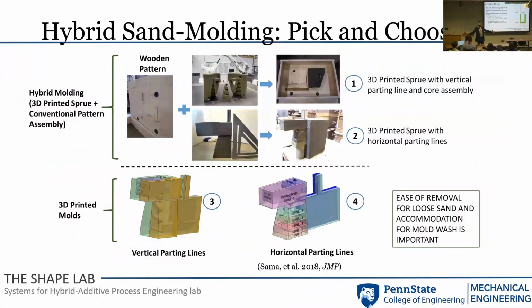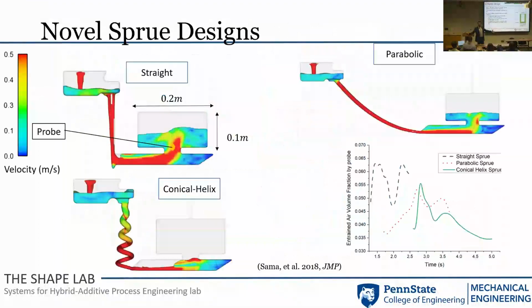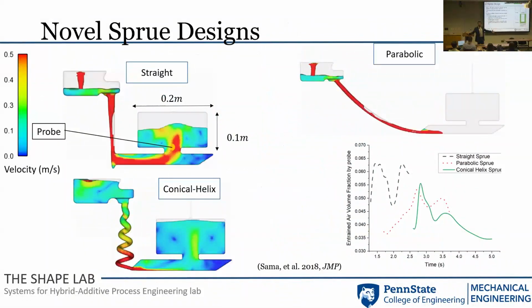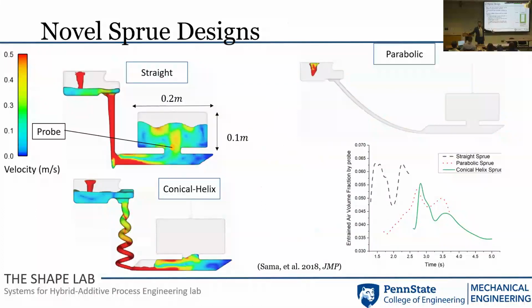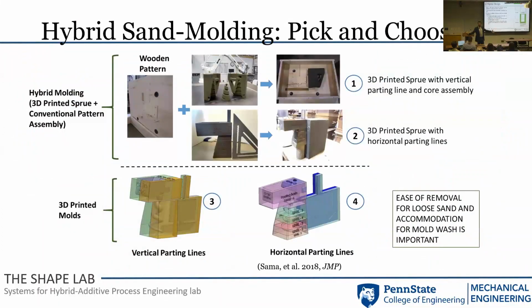Absolutely. So the answer is yes, but it doesn't apply just to our conic, it applies to any sprue design. So the way we have written the algorithm, we are assuming whether it is straight or conical helix, you're going to have the same amount of superheat. The alloy is going to have the same surface tension and so forth, and they both are going to have mold wash and stuff. So the constraints that we have is the temperature and the velocity of the metal that enters the mold at this point should be the same. So like for example, in this particular case, we have these different sprues that are not attached to the regular mold, so it's still away from it.